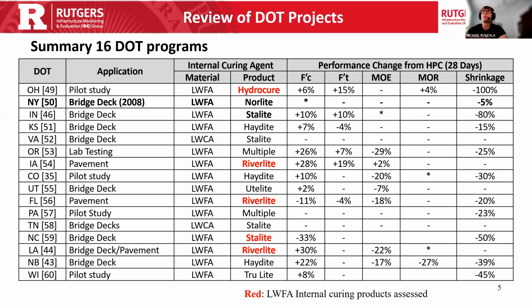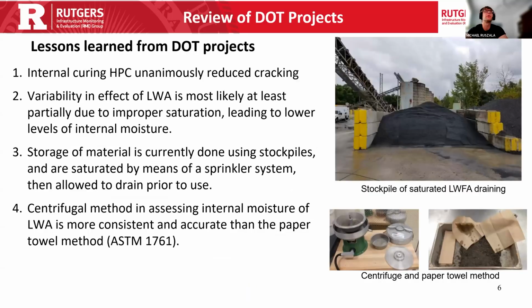We looked at the performance change in these HPICs compared to the conventional HPC. It's found that in most cases, the results were very similar. There wasn't much of a difference between the control HPC and the HPIC. That's favorable. The workability was very similar, castability was similar, strength properties were similar. But one thing that was observed was in all cases a good degree of shrinkage was reduced, and in some cases a very high degree of shrinkage, especially with autogenous, which we'll go into a little bit as well.